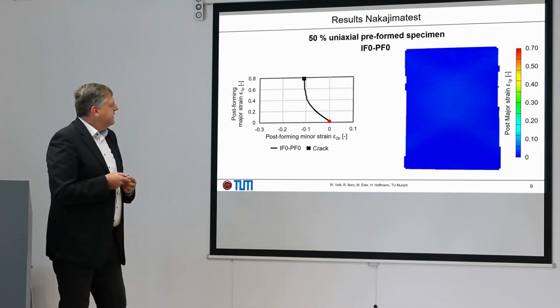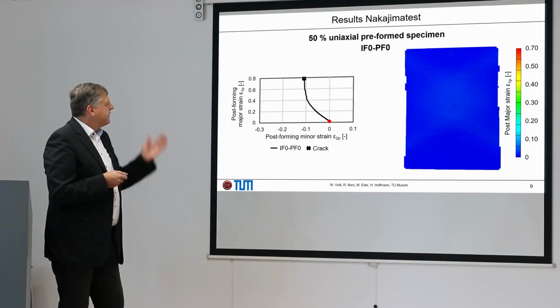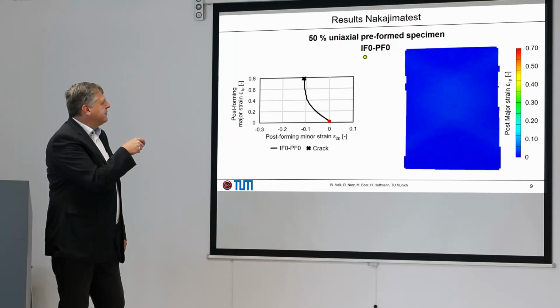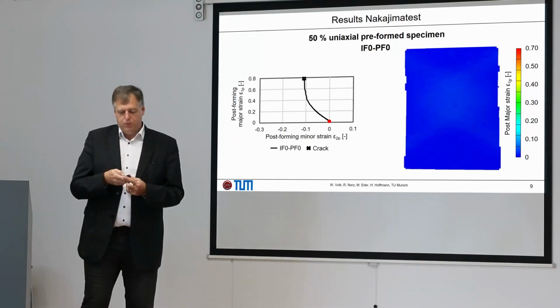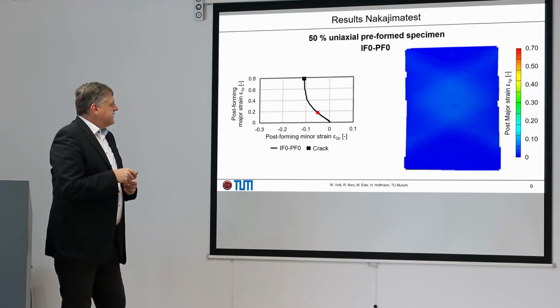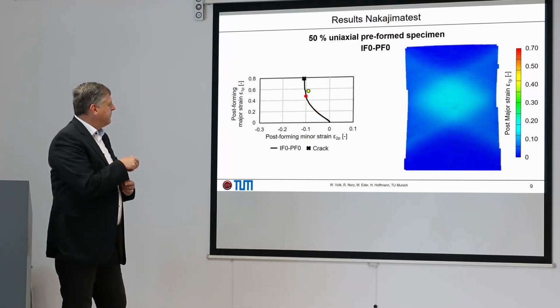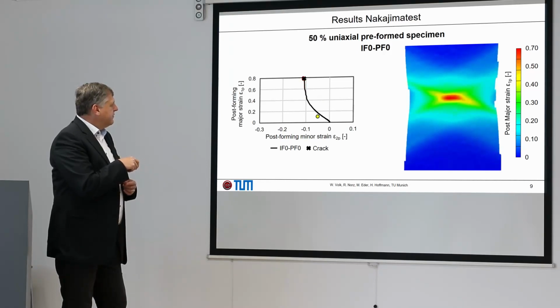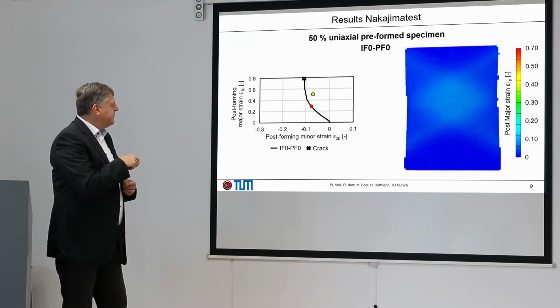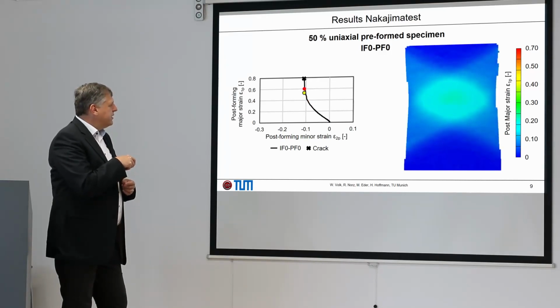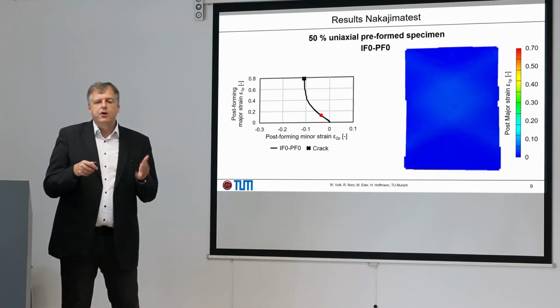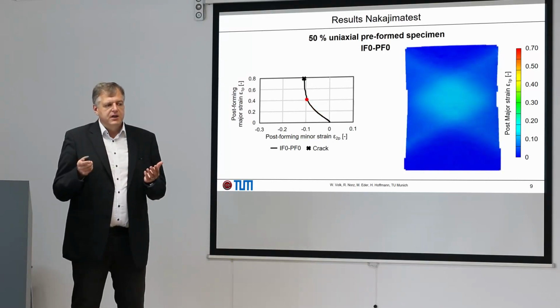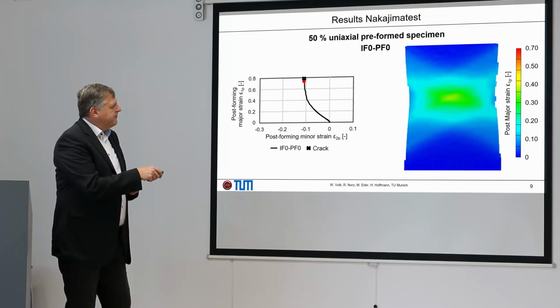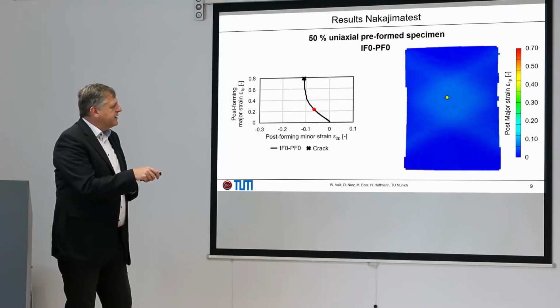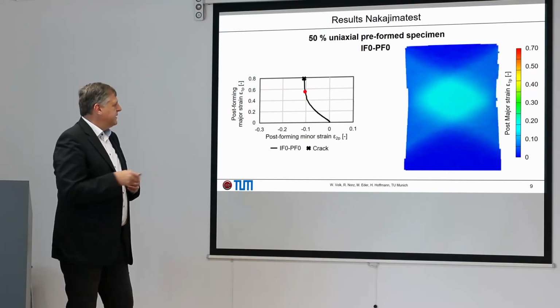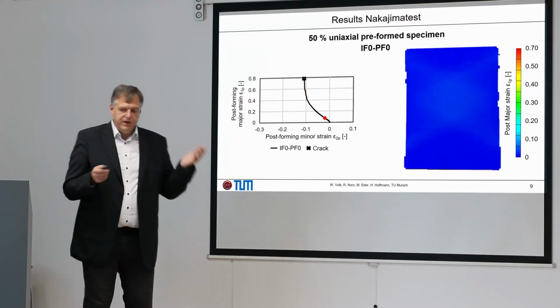Here now we see the behavior with 50% uniaxial preformed specimen, 0-0 combination, so the classical one. We see the start of diffuse necking, and then we go to the plane strain behavior, where we know that with this point we have some microvoids which can occur because of the 3-dimensional strain state, and finally we have the start of localized necking starting out of the mid of the specimen. So this is well-known behavior.